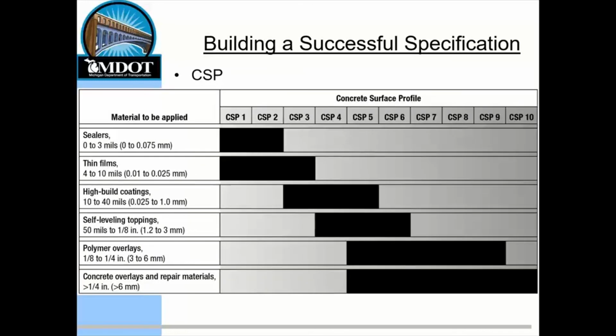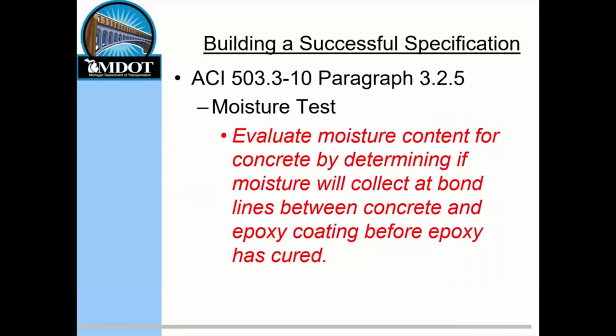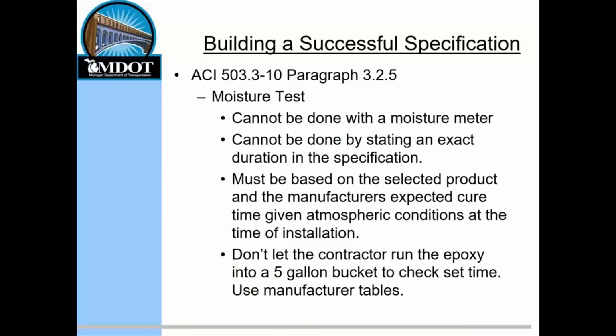Here you can see this is just the ICRI table that talks about where you should be for different surface profiles. Moisture tests: the ACI spec says to evaluate moisture content of concrete by determining if moisture will collect at bond lines between concrete and epoxy coating before the epoxy is cured. That doesn't specify a moisture content percentage. Some people try to use a moisture meter and make it an exact science. In Michigan, we don't use that and we don't allow it. We go with the ASTM D4263 moisture test, which requires a 4-foot by 4-foot polyethylene sheet taped to the deck.